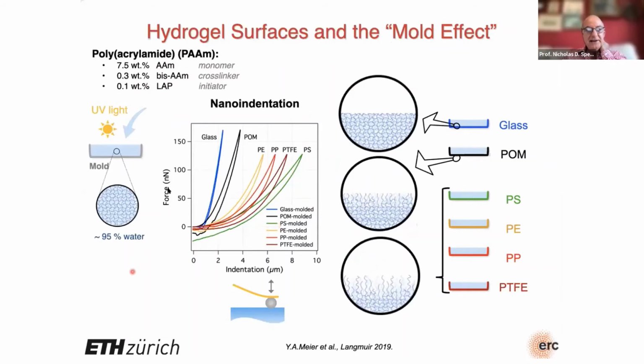Now, this is quite a busy slide, but let's start from the top left. This is the material that I'm going to be talking about mostly today, polyacrylamide that we make in a very simple way using UV polymerization. So it's a cross-linked system. It's about 95% water. And what Jian Ping Gong in Hokkaido University found about 20 years ago is that depending on how you mold it, depending on this mold surface, you get different behavior on the surface of the gel that was in contact with that mold. And this is some work we did, just extending what she did using a whole bunch of different mold materials. And you can see in all cases, except for glass, with all of these polymers, we got a much softer surface when we indented using AFM. So we use our colloidal probe AFM as an indenter. And I'm going to be talking about many of these kinds of experiments.